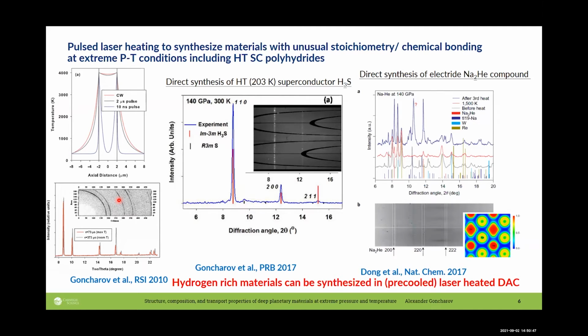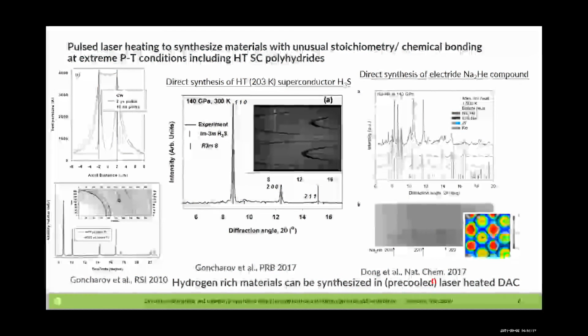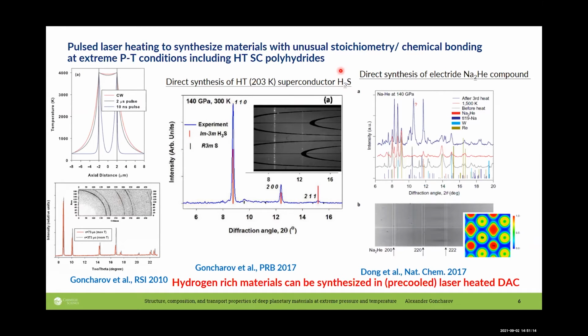But on this slide, I would like to show you the importance of pulsed laser heating with microsecond pulses for synthesis of new materials. Because in certain cases, you cannot just laser heat materials continuously, for example in the presence of hydrogen, because hydrogen diffuses into the diamond anvil cell and breaks it. So for example, we synthesized the high temperature superconductor H3S from elements, which is a 203 K high temperature superconductor. At 140 GPa and more than 1,000 degrees, we synthesized the material H3S.